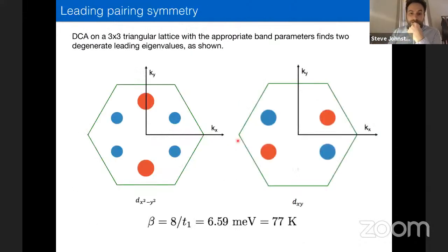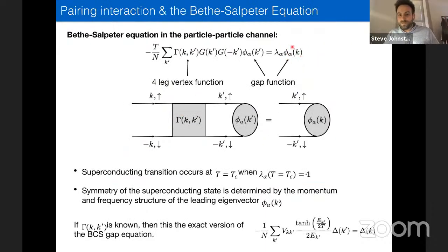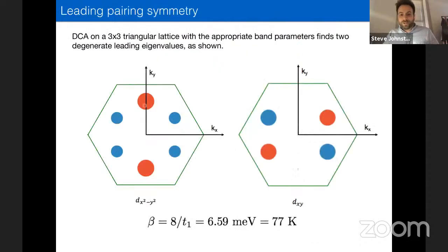And so when we do this for our problem, again, we look at a 3x3 triangular lattice model. What we find is that there are 2 degenerate solutions that have the same eigenvalue as a function of temperature. They're the leading eigenvalues. One corresponds to the x squared minus y squared symmetry. The other corresponds to the xy symmetry, dxy. What's shown here is the phase of this pair function, or the eigenvector, in the allowed momentum points in the cluster. The size of the dot is the strength of the eigenvalue, and the color is the phase, right? So this is plus, minus, plus, plus, minus, plus, and so forth. And these calculations are done at a temperature that corresponds to about 77 Kelvin in real units.